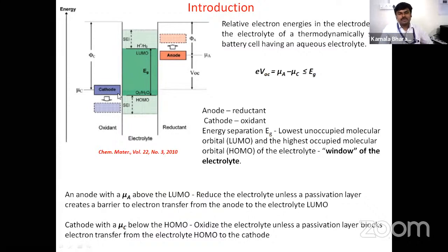The way we have to choose the cathode and anode is such that, for example, the chemical potential of a cathode should lie just above the highest occupied molecular orbital of a liquid electrolyte. If it lies below, then it will start to oxidize the liquid electrolyte. In the same way, in the case of anode, the chemical potential should lie just below the lowest unoccupied molecular orbital of a liquid electrolyte. Otherwise, it will start to reduce. So the difference between these two chemical potentials, mu A minus mu C, decides the open circuit voltage of a battery.